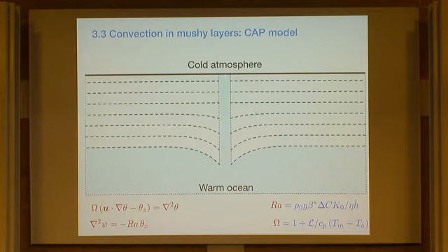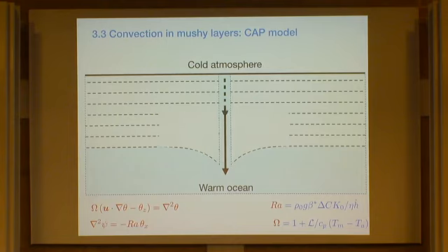Cold on top, warm beneath, and this is a self-sustained process, but I'm going to start my explanation in one place. So if there's cold liquid flowing down a channel, it's bringing material which is relatively cold from above. That relative coldness is conducted into the mushy layer to the side, setting up a horizontal temperature gradient.